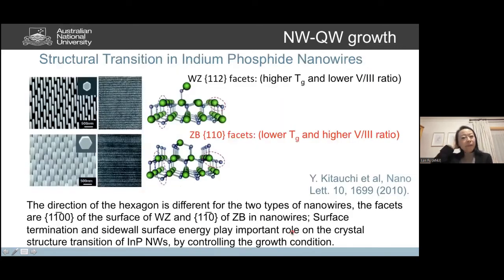It turns out that if you look carefully in the literature, people can actually grow indium phosphide nanowires with different facets. I have mentioned that the indium phosphide nanowires we grow are wurtzite indium phosphide, based on a high growth temperature and low V/III ratio growth. This Japanese group has shown quite nicely that if they change the growth window to a lower growth temperature and a higher V/III ratio, they can change the nanowire to zinc blende. You can see that although they all have hexagonal shape, they actually have rotated facets. Because of this, they create this zinc blende 110 facet on the top.